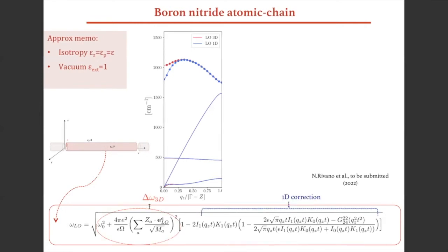Indeed, if you focus on the dielectric shift term, so after the plus, we can identify two contributions to the final shift. First of all, this term is basically the well-known three-dimensional LO-TO splitting we are familiar with. Then in the brackets, we have the proper 1D behavior of these polar optical phonons.